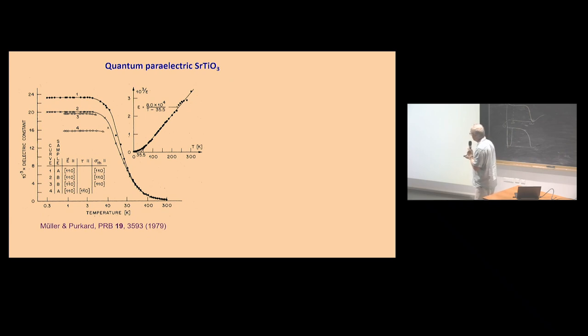And this paper from Müller is highly cited, because strontium titanate is the source of many other investigations. And by the way, Alex Müller studied strontium titanate his whole life. And by the way, he discovered high-Tc superconductivity, which was a completely different topic. But strontium titanate inspired him, because if you slightly dope strontium titanate with calcium, you observe superconductivity in such an insulating system. You observe it in the millikelvin temperature range. So the question was, what happens here at low temperatures?